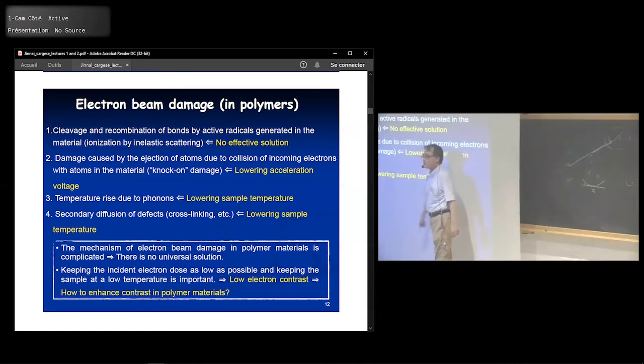Temperature rise. You shine the electrons, then you vibrate the molecules, and then it's a phonon, right? And then it raises the temperature. And there's a solution for that. We can lower the temperature. So we can observe the image, and then we cool the sample to a cryogenic temperature, like minus 170. That's the thing you can do.